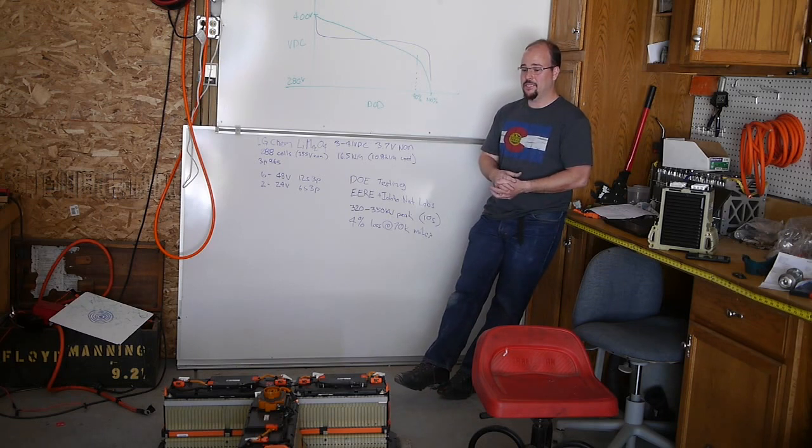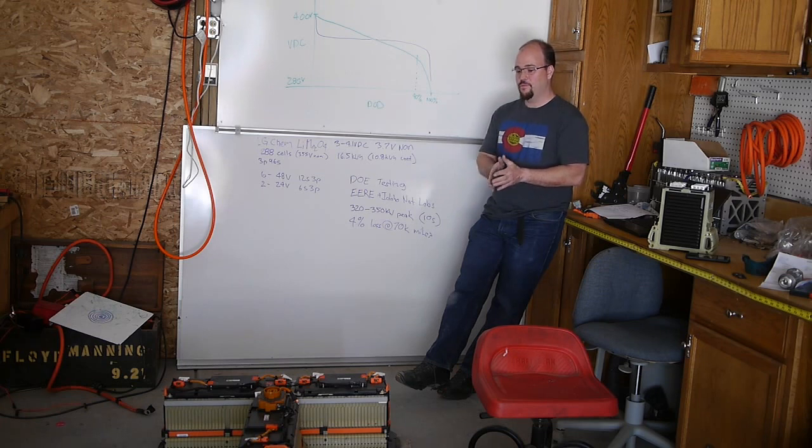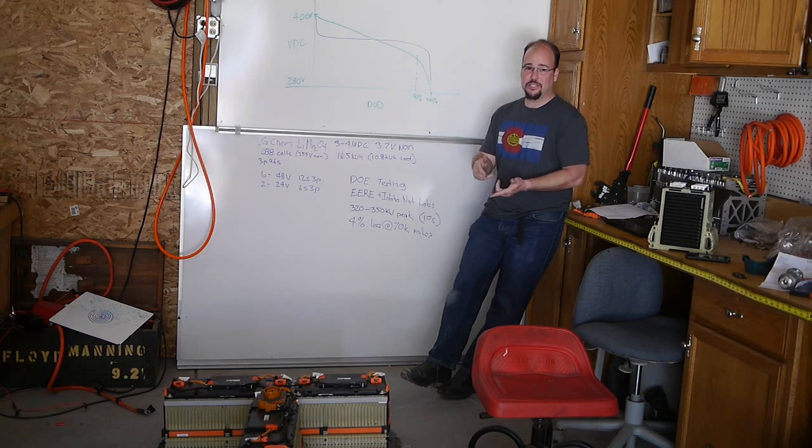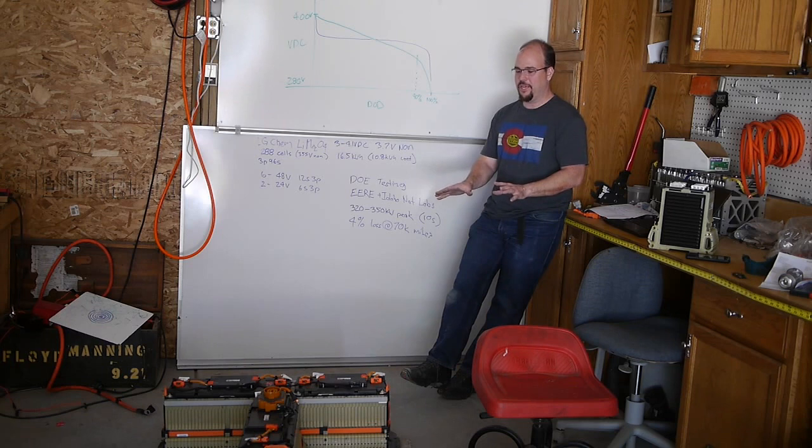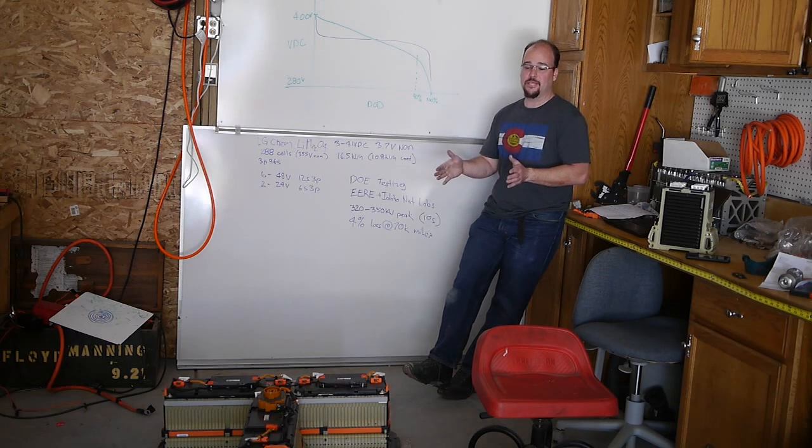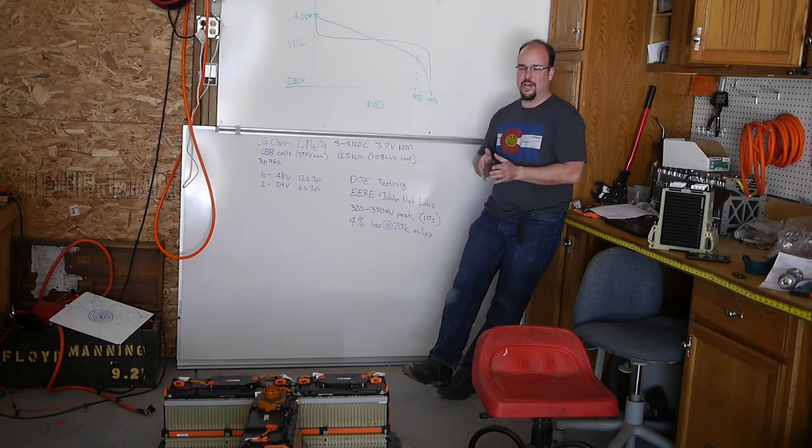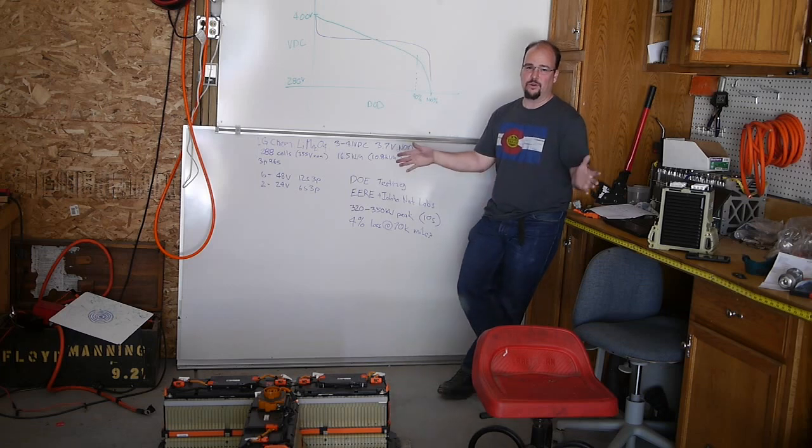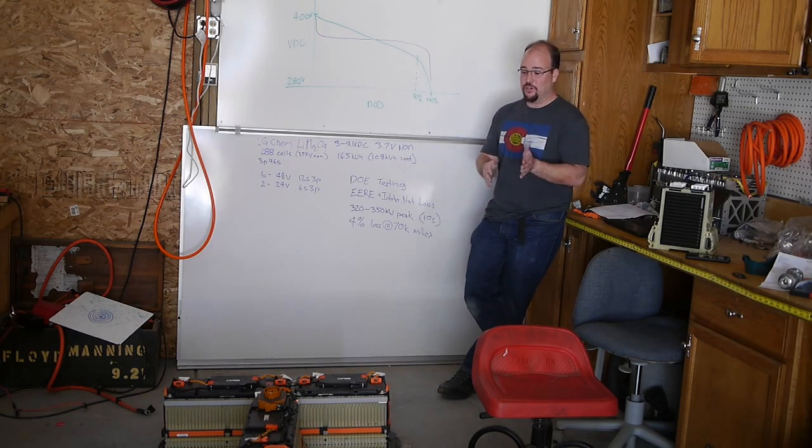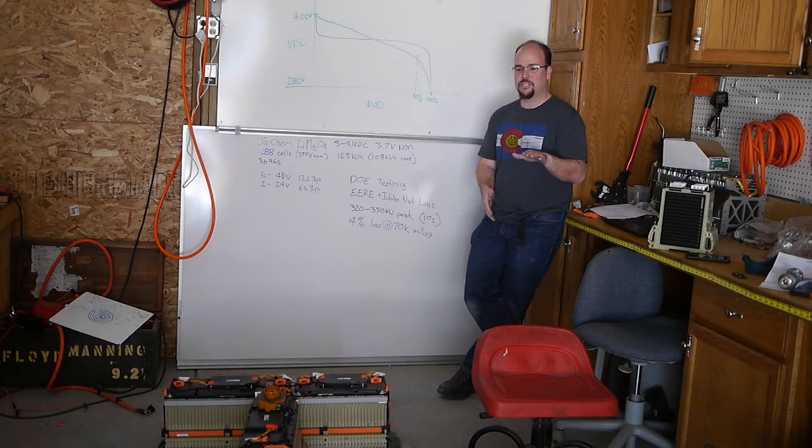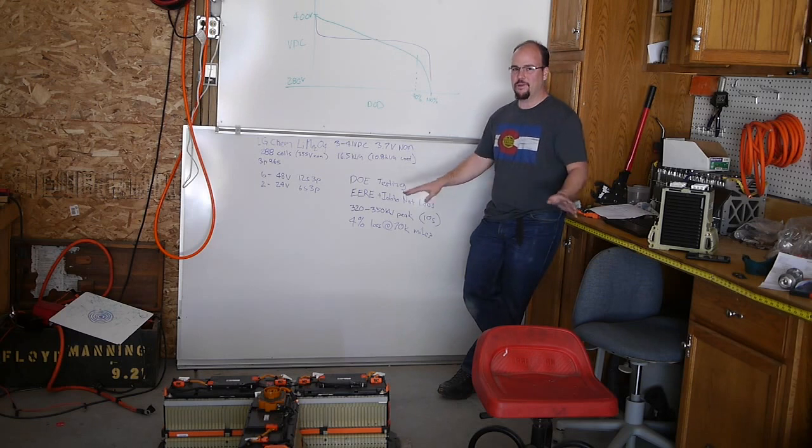Now, the way that EERE actually tests it, at least the procedure that I've read, is they will start with a fully charged battery, discharge it for either 10 seconds or 30 seconds, depending on the test standard, at the highest power output that they can get out of it. And then they'll stop and they'll let it rest, and then they'll do it again, and then they'll stop and they'll rest.